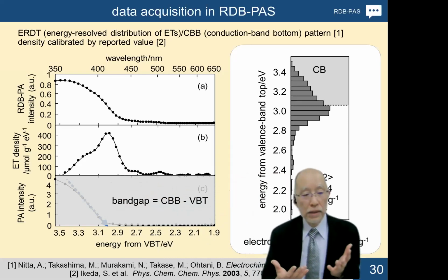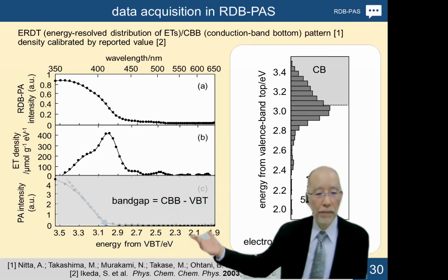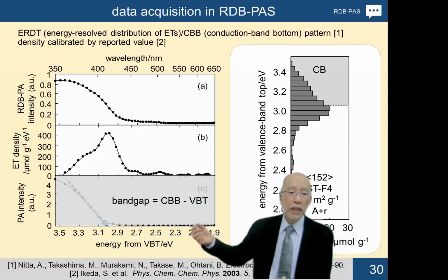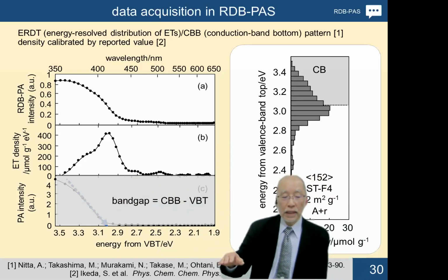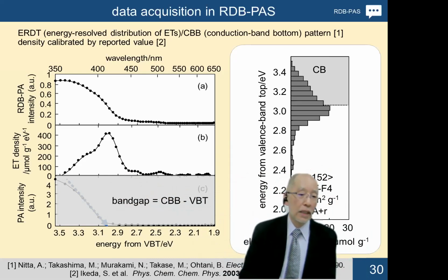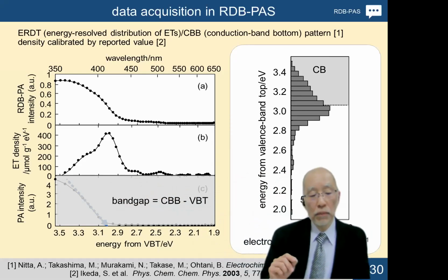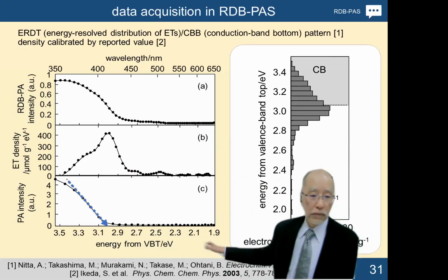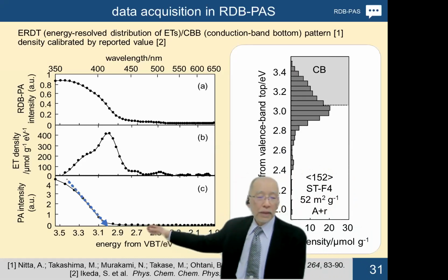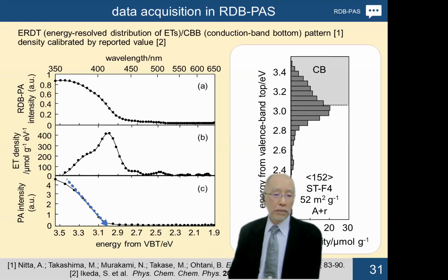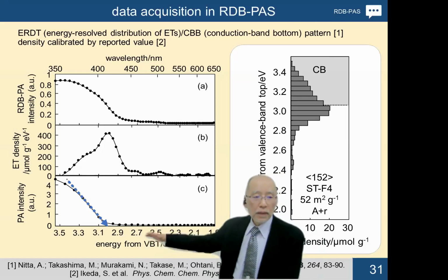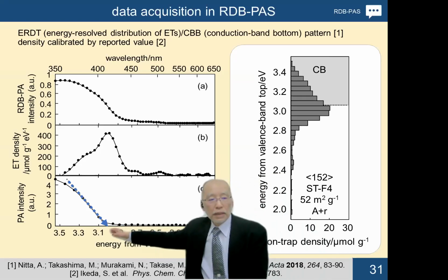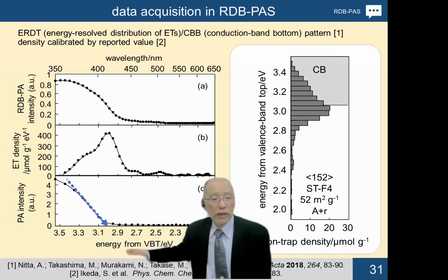And by using the same instrument with single beam measurement, that is just the ordinary PAS spectroscopy, it is possible to measure the photoabsorption spectrum-like signal. That is something like this. That is almost the same as the absorption spectrum or reflectance spectrum of samples. And it is possible to determine the band gap from the photoabsorption edge wavelengths.